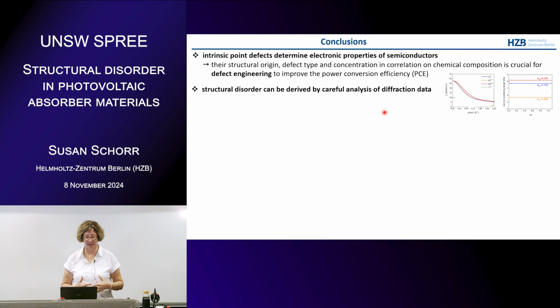I want to show you that the intrinsic point defects are really important to study because they determine the electronic properties of the semiconductor. And it's also important to know their structural origin. Not only the levels, but also which defect you have. Because then you can do defect engineering to improve the power conversion efficiency of the solar cell. And we derived the structural disorder by careful analysis of diffraction data where we used X-rays and neutrons.